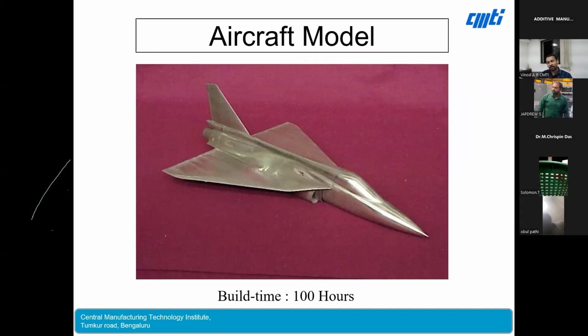It took around 100 hours to realize this part by the 3D printing process. The same thing we fabricated through the conventional process also. It took more than 1.5 months. So that 1.5 months by the conventional route has been reduced to 100 hours by this additive manufacturing route.